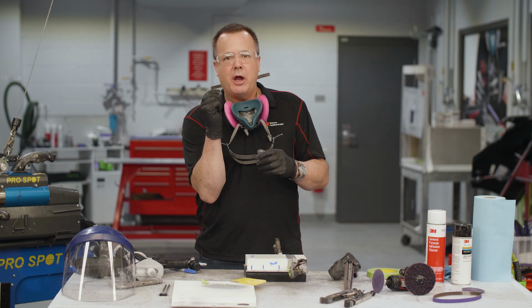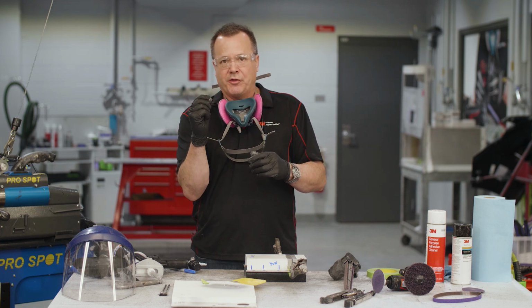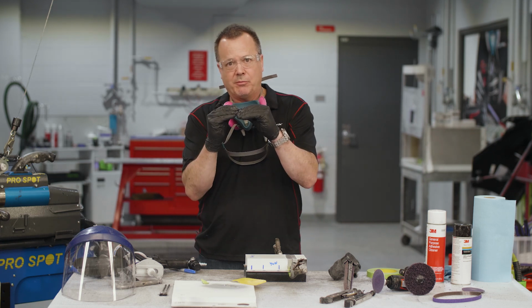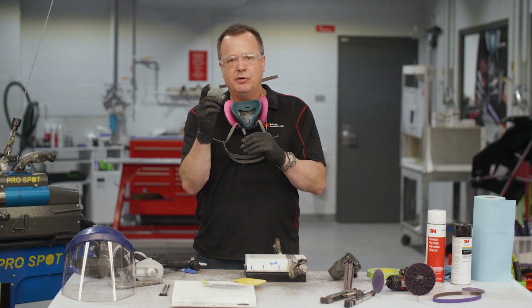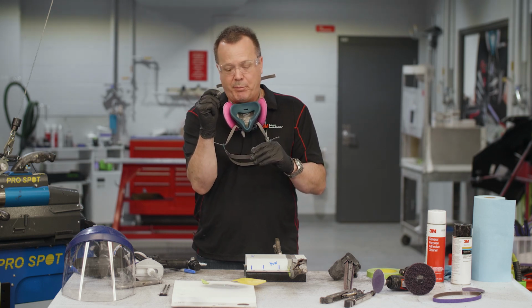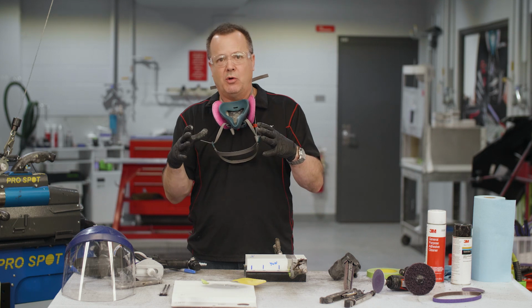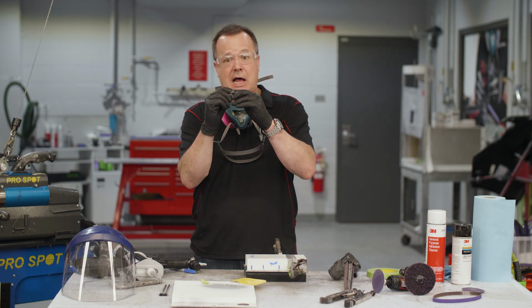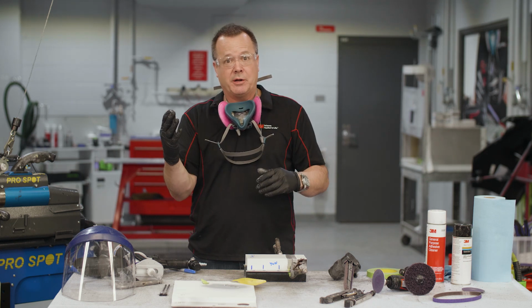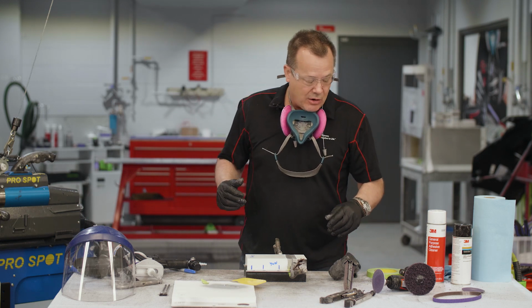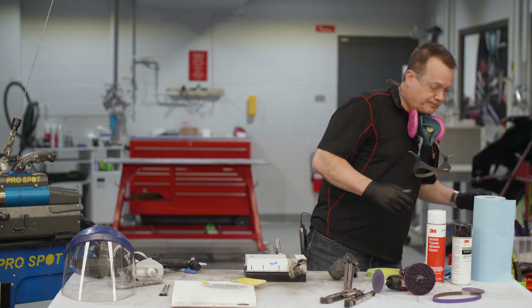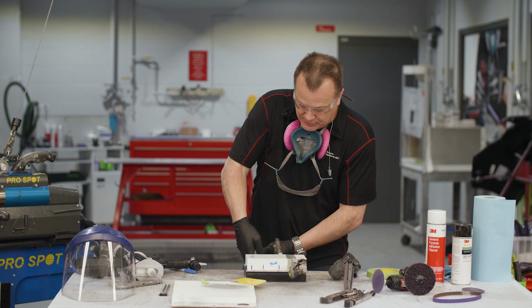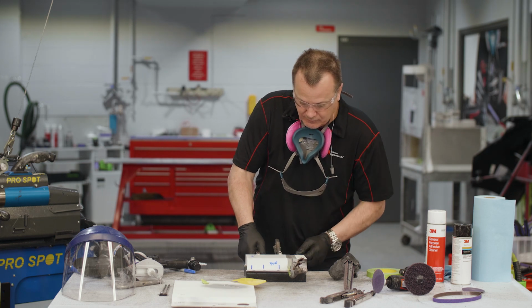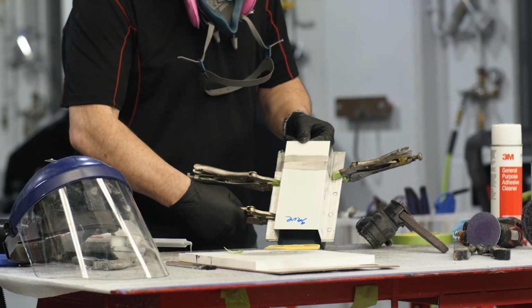We don't want to be drawing those panels together with the pressure of the machine. We want to already have them tightly fit up, because if you use your welder as a clamp to pull the panels together, that's where you get holes blown through the panel. Once that weld nugget gets hot, the panels will spring back open, and you'll end up with a hole. So we want to clamp those down nice and tight. Let's put one more clamp in here. Okay, so all clamped up.